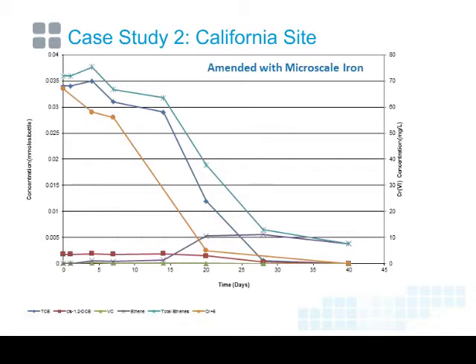So in the treatment amended with microscale iron, you see very rapid degradation. One thing to point out was that the hexavalent chromium was so high that the water was yellow. So it was pretty toxic water. And what we saw amended with iron is we saw the hexavalent chromium drop out very quickly and down to non-detect concentrations within 40 days.